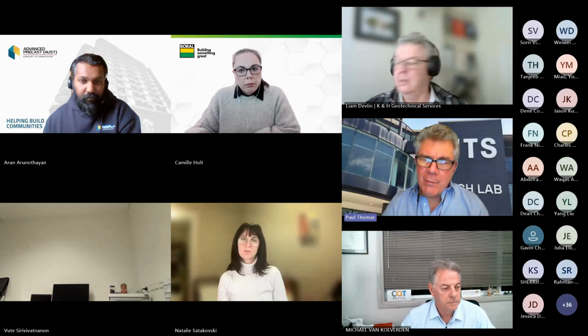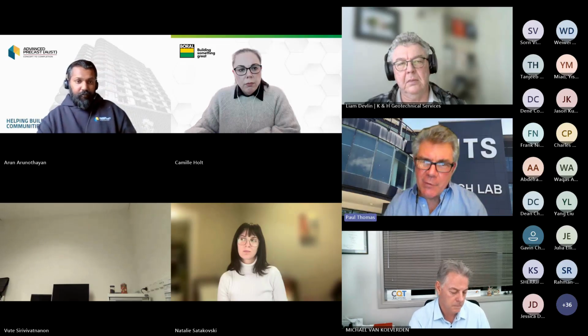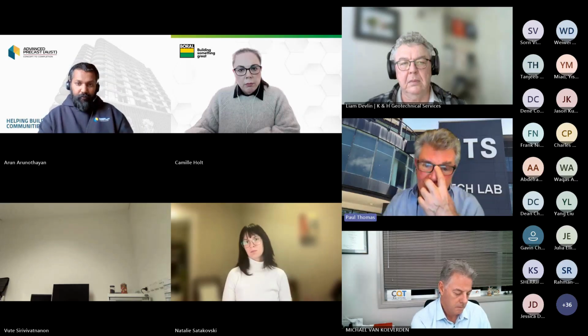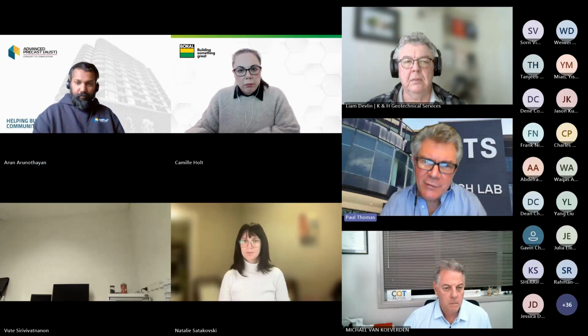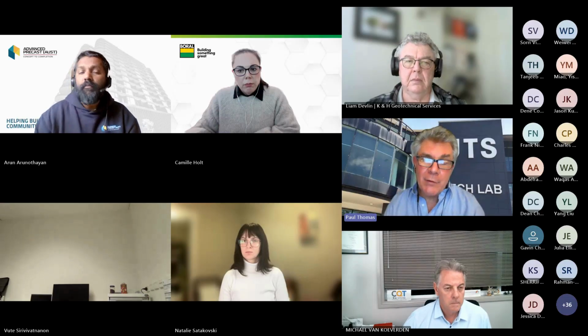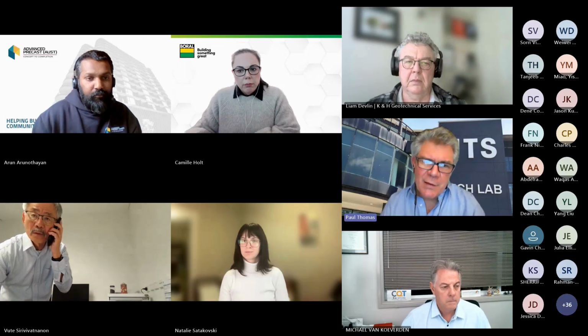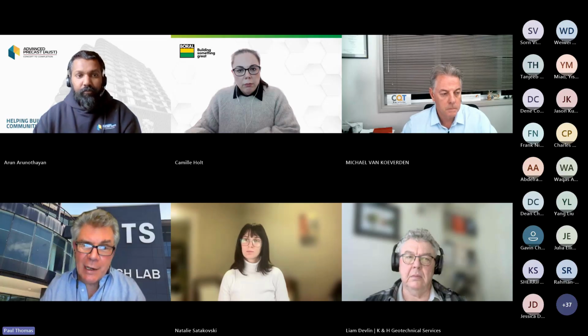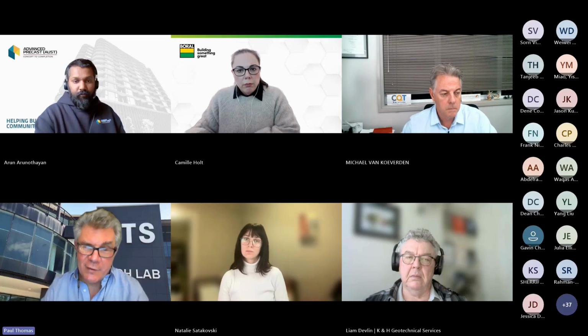Hello Michael, good to see you. The answer to that is no, we haven't done that work. However, if you do the calorimetry of paste and mortars with equivalent substitution levels, they're actually fairly similar. Sometimes you have a sulfate imbalance if you overload with calcined clay, but really there's no increase, just a slight acceleration, but very little difference between the two. Admixtures do make a difference however - admixtures can retard the hydration. So if you need to put a lot of admixture in, you get a bit of retardation, and that actually reduces the heat.